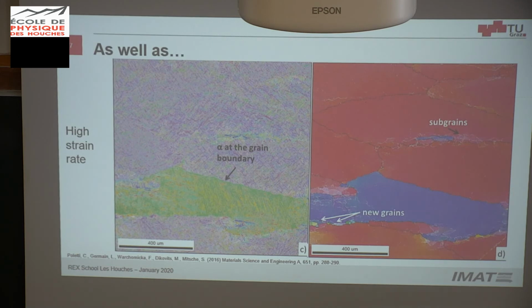And there are still a lot of publications because it's very difficult to get these kind of results where you quench immediately after the deformation. Especially when you go to very high temperatures, it's very difficult to really quench and have in situ experiments. And this is important for us afterwards for the modeling. We are not modeling discontinuous dynamic recrystallization with critical strain and so on.